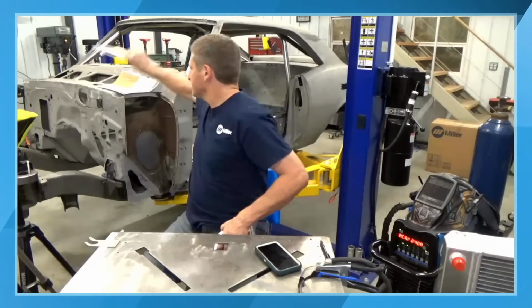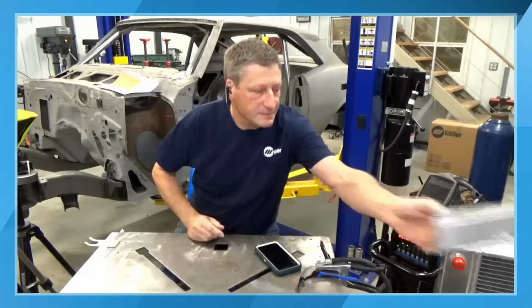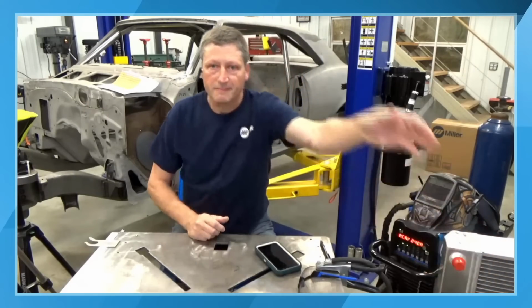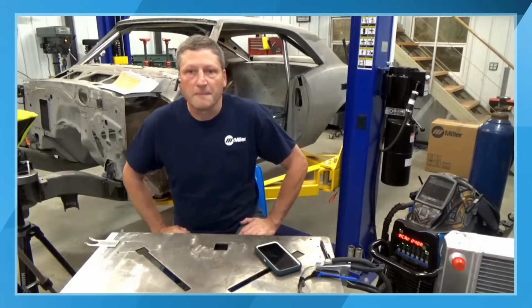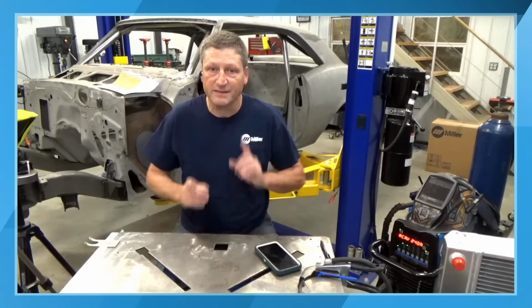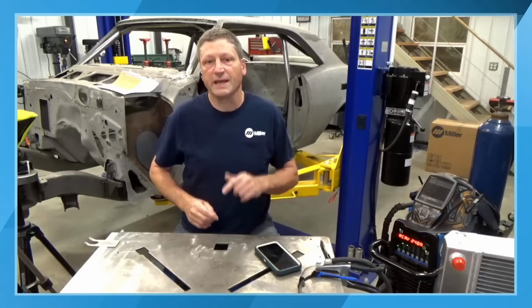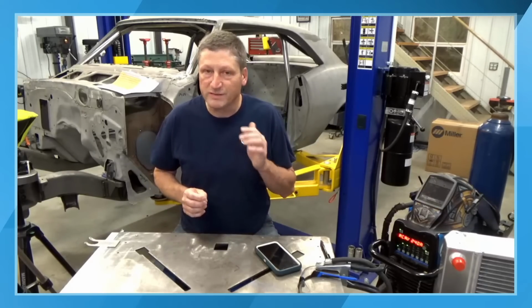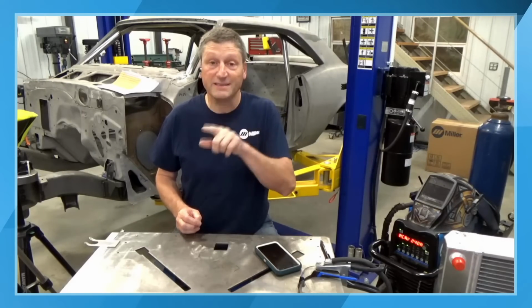So we did get a couple of questions, Andy. What's the scale of difference between an A rating and a C rating? Oh, it's a lot. C would not be recommended. It's the next lowest, besides not even checking the box. So, for example, if you're looking for post-weld heat treating, 4943 can be post-weld heat treated, but 4043 can't. And that's a very close alloy. They're almost in the same family. So the 4943 can, but the 4043 is not recommended, and it's a B. So that's A and B.